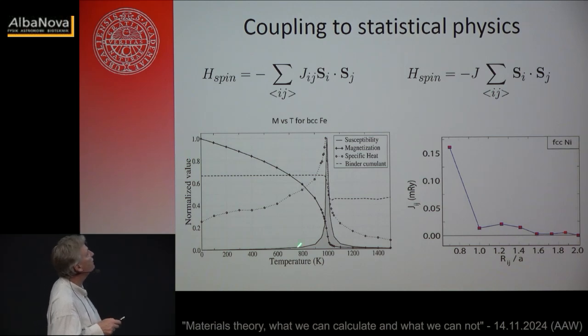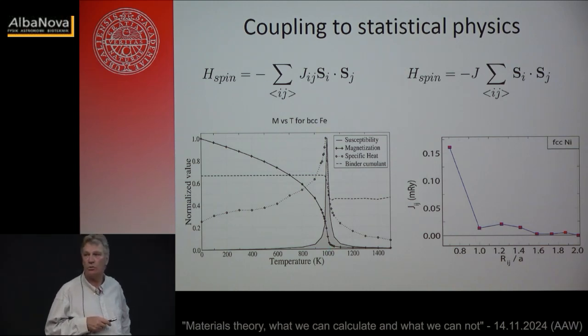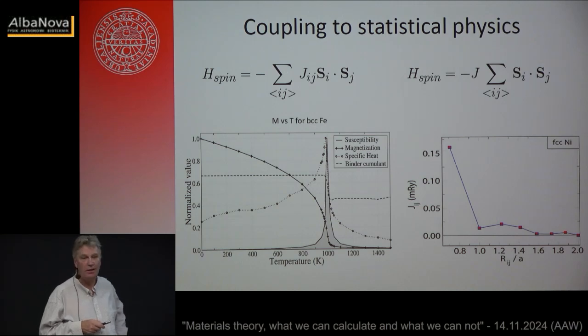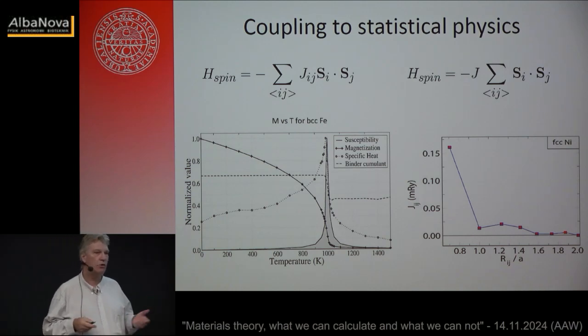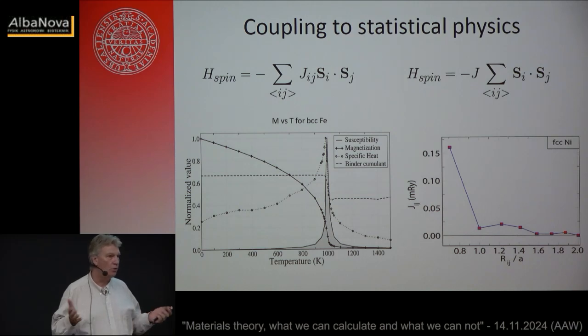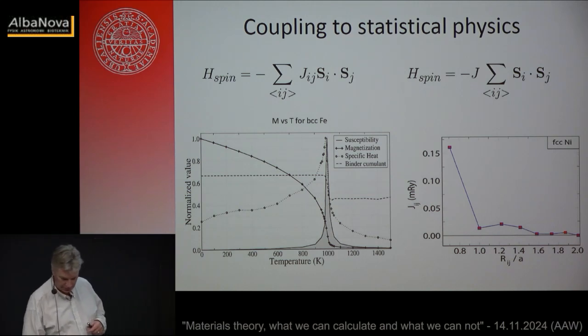And so you see now that the specific heat, susceptibility, specifically this guy here, it has this sharp peak right where the simulated ordering temperature is, and that points to a critical temperature of around 1000 Kelvin, which is pretty much close to where the experimental ordering temperature is for BCC iron. So this is now a tool where I would say we can calculate the size of the moments, we can calculate the ordering temperature, we can calculate the nature of the magnetic ordering, everything comes out. So it's basically a ready-to-use tool, I would say.